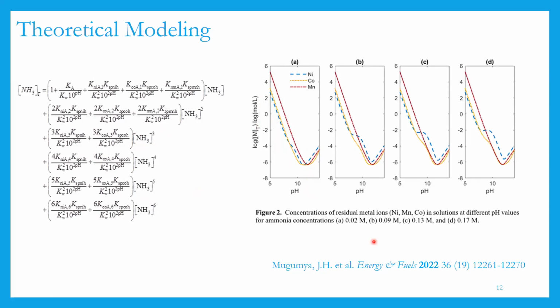This was done for 4 different concentrations, and the experiment was carried out for 2 of these. We carried it out at different pH values. And then for 1 round of experiments, we used different ammonia concentrations, but we maintained the same pH.